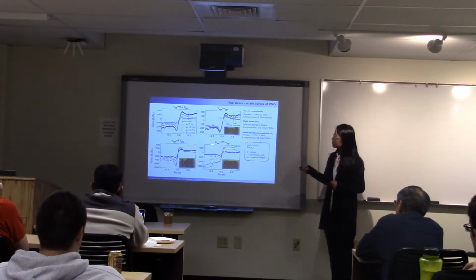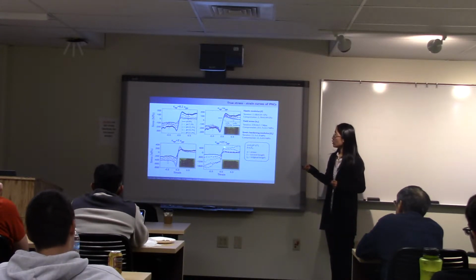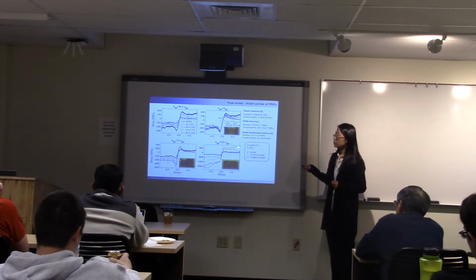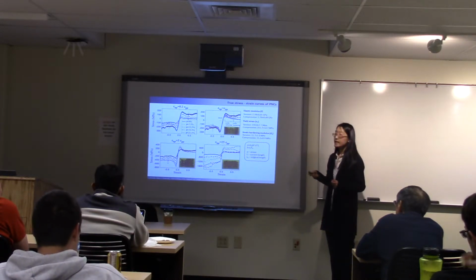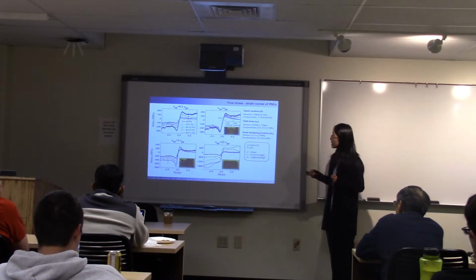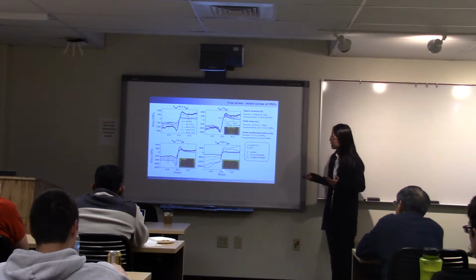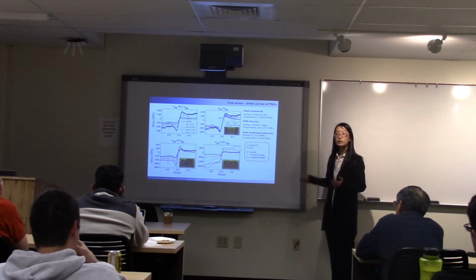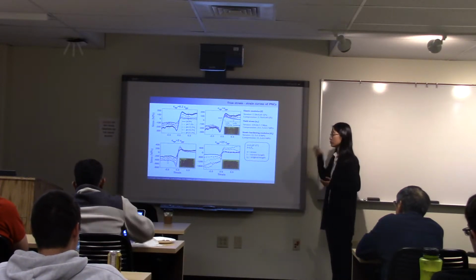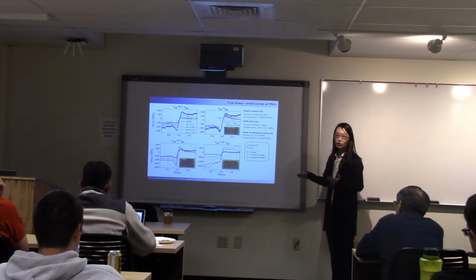And when we further increase the nanoparticle-polymer interaction strength, we find the reinforcement again in the tensile loading domain in the plastic region. Especially when we have a very high nanoparticle volume fraction, the original strain hardening is resumed again. So we can also see from the snapshots that the uniform deformation is resumed again instead of this localized deformation or nanoparticle agglomeration.